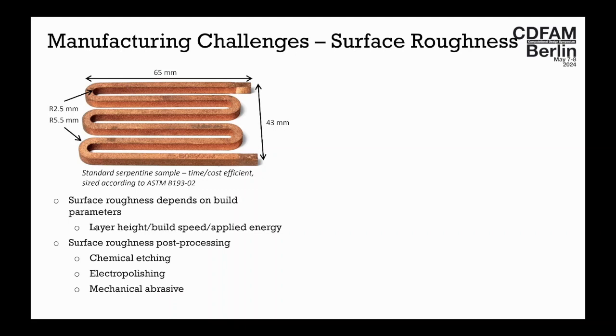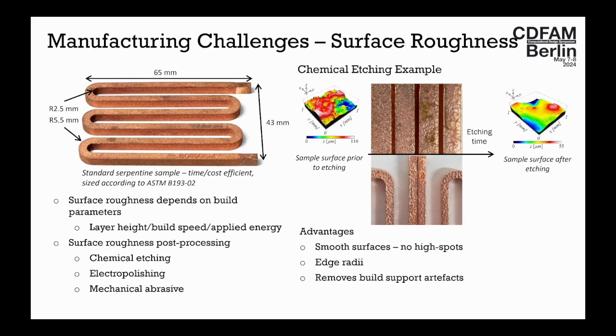Surface roughness is a significant issue, and because of that, we've put an awful lot of time and effort, or one of my material scientists has, Priya Munagala, in developing chemical etching processes and electropolishing processes to be able to remove or eliminate that. One of the advantages to the fact that we're using chemical and liquid processes is that they are cheap, they are sustainable as far as possible, which means that we can have an economic compromise. So we can print faster, which tends to lead to much rougher surfaces, but it's cheaper because you're spending less time on the machine. But we can use a relatively cheap process to then post-process and reduce that surface roughness. And so we can make some economic gains there.